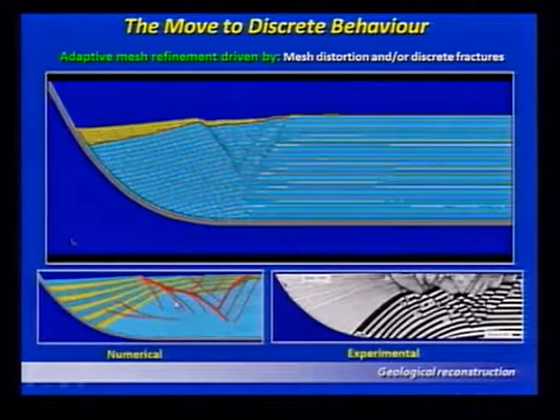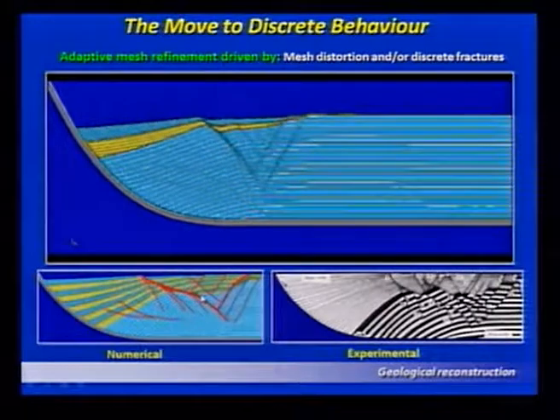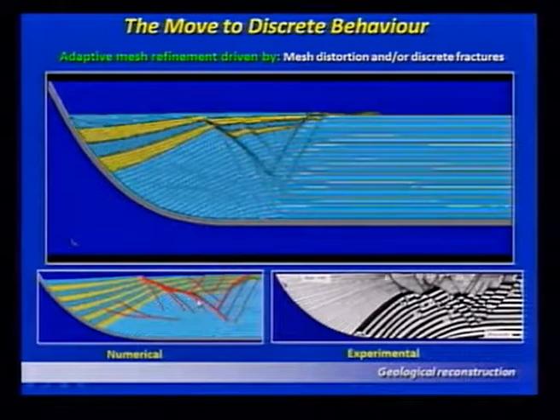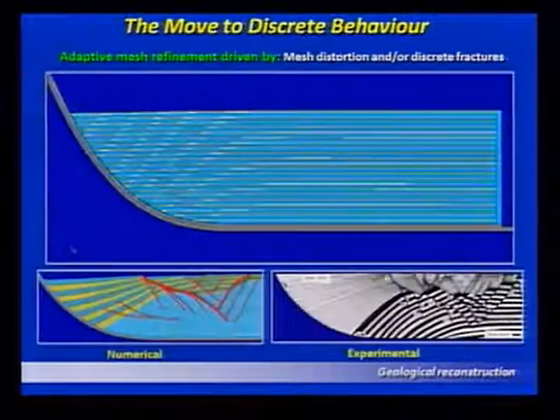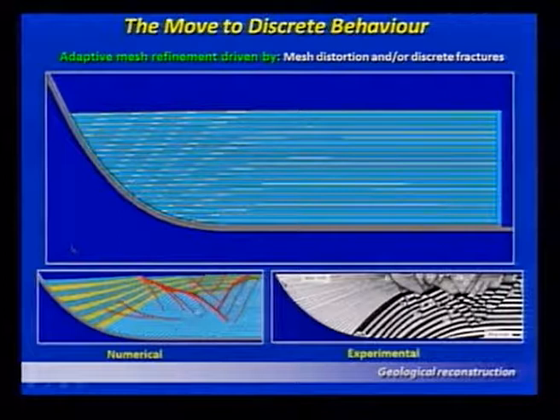And this is a comparison of the numerical solution with the experimental solution. And what you find is that you actually replicate the essential features of the problem. The shear bands that you develop there are very similar to the shear bands that you see.